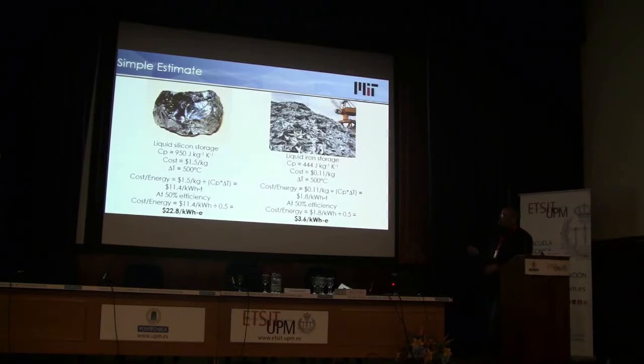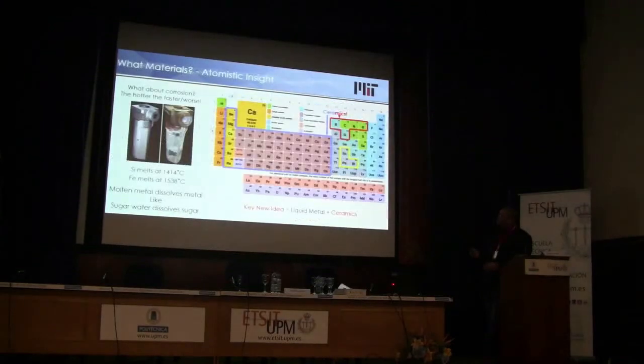Conversely, you could imagine going to something else like scrap iron, scrap steel. You can get another order of magnitude cheaper, down to about $3 or $4 per kilowatt hour electric. So this is where it's attractive from the standpoint of what materials you pick. And there's an interesting thing that happens with respect to corrosion, which we had not really thought about until we started this.